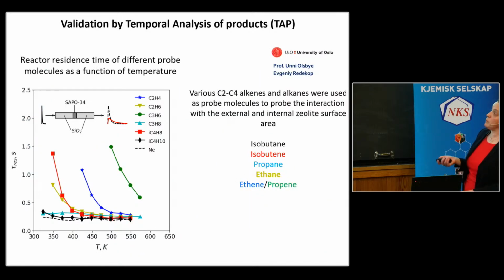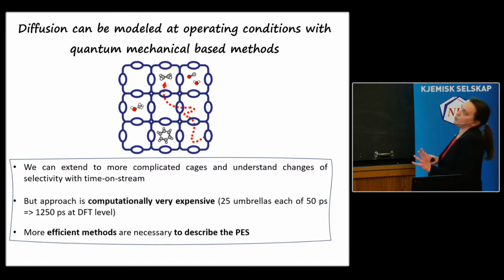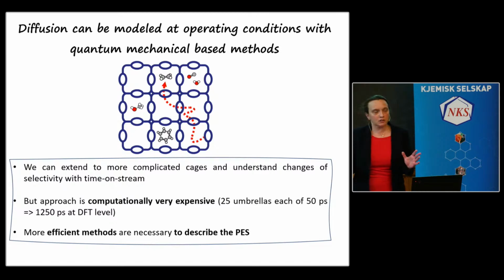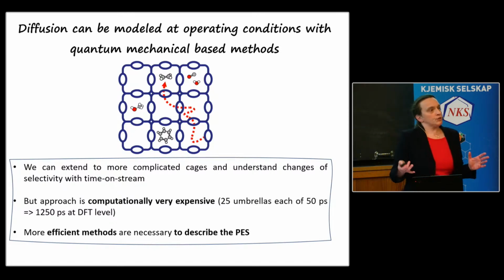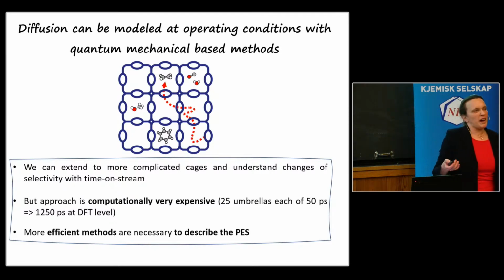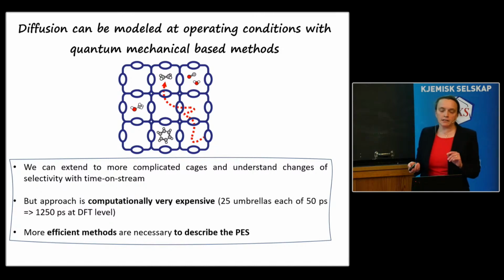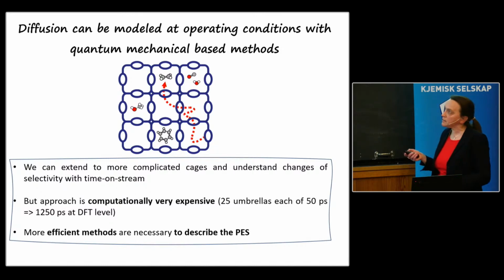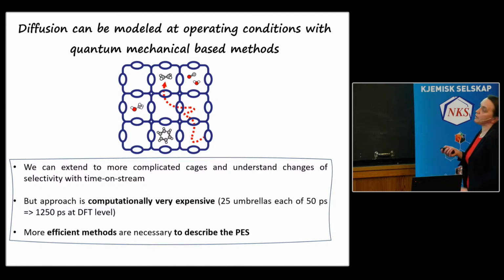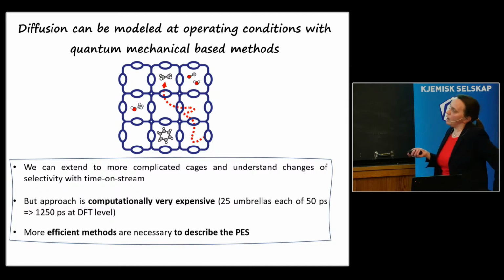And these are the TAP experiments where you have mean residence times in terms of temperature. We can also see, for example, here that for propene and for ethene we have higher residence time. So it was again a confirmation. So this shows us that diffusion we can also understand at the molecular scale, but it's rather complex to model, let's say. We need very expensive techniques. And in the last few slides, I want to show you, because what we did here, we did everything with DFT. So this is computationally very expensive.